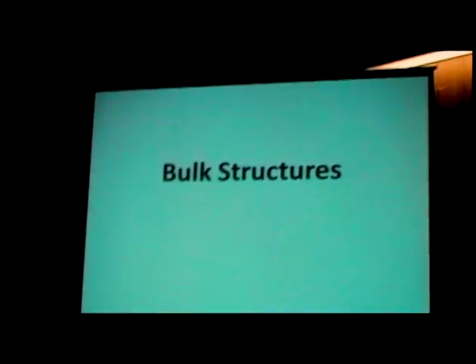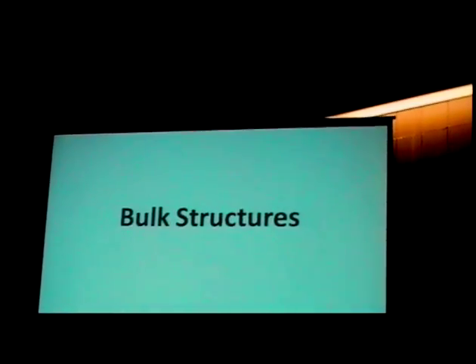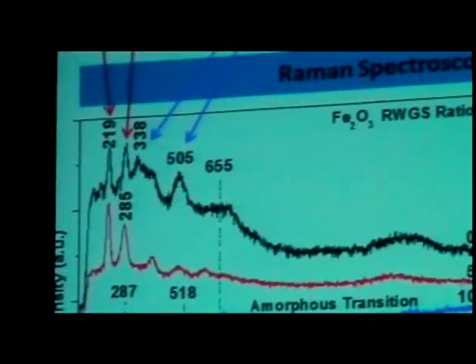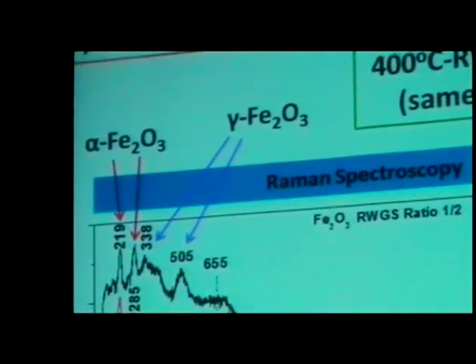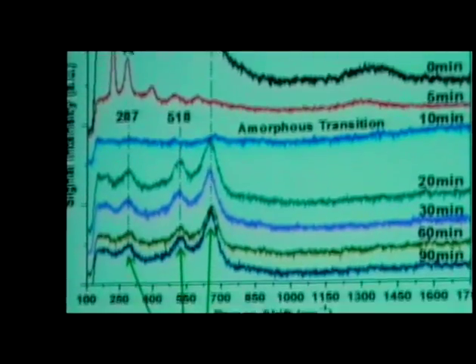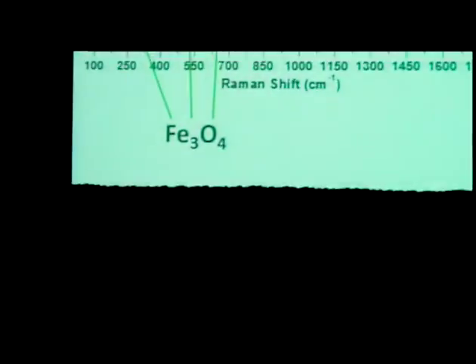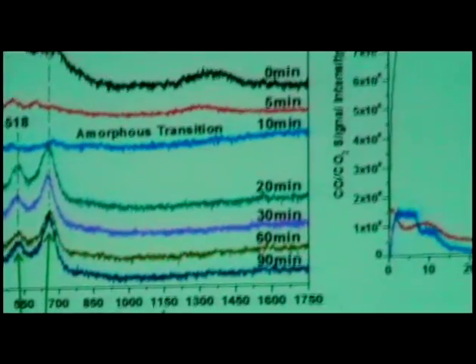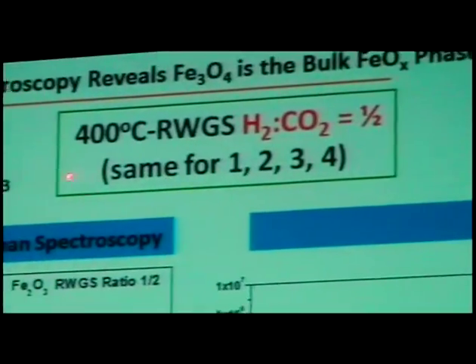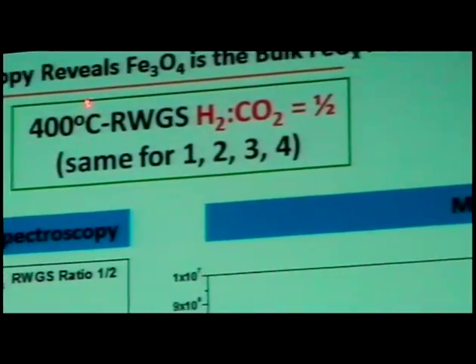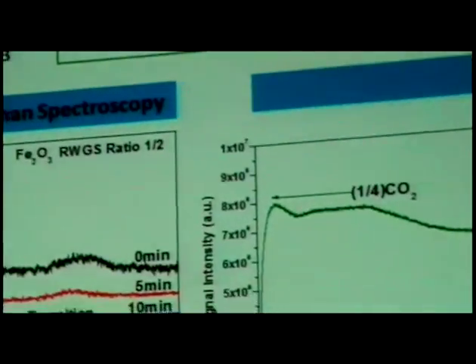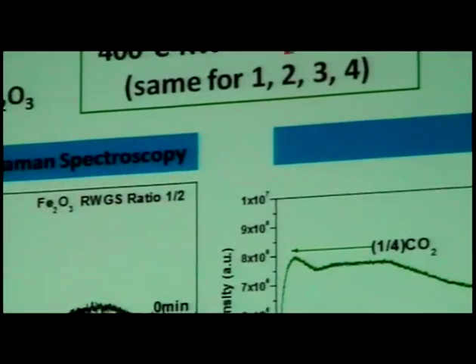So the first question is bulk structure. What is the bulk structure of these iron oxide-based catalysts? And this is done here with Raman spectroscopy. This is the intensity, and here you have the various vibrations. And this is pure iron oxide. We examined this for many, many different H2 to CO2 ratios at this temperature, and actually also looked at some different temperatures as well. Basically, the results were the same.